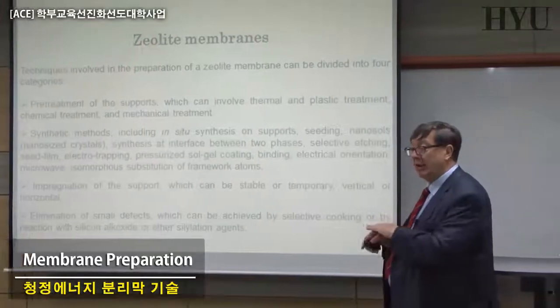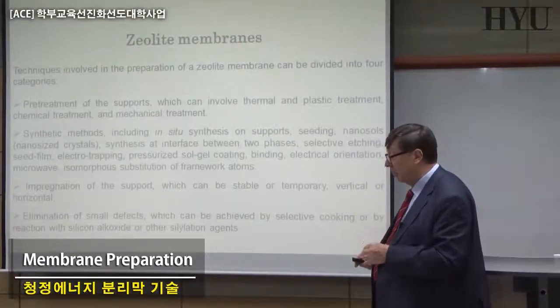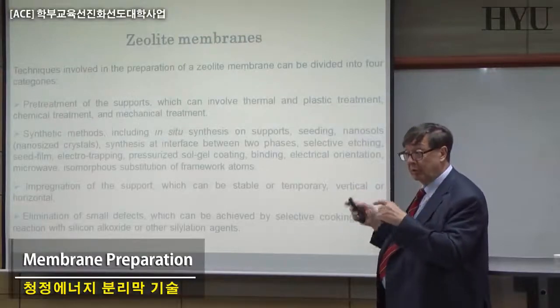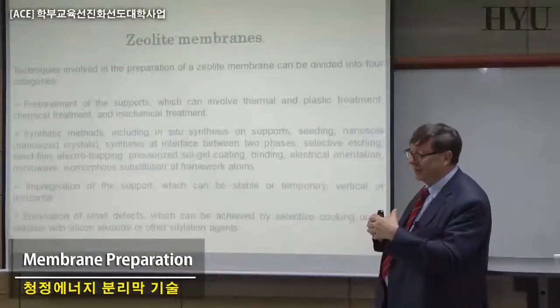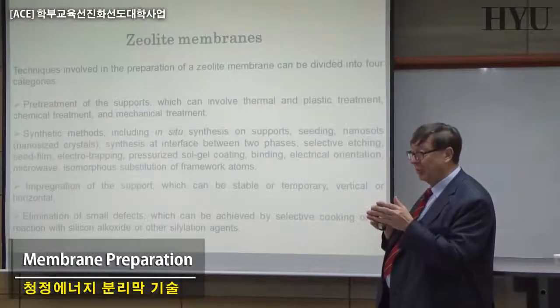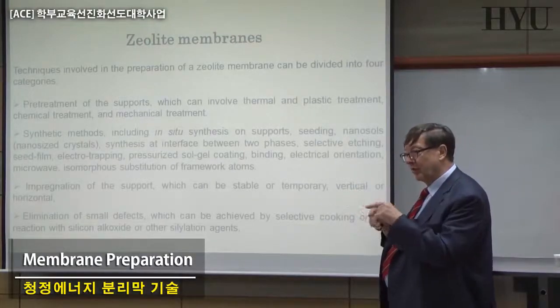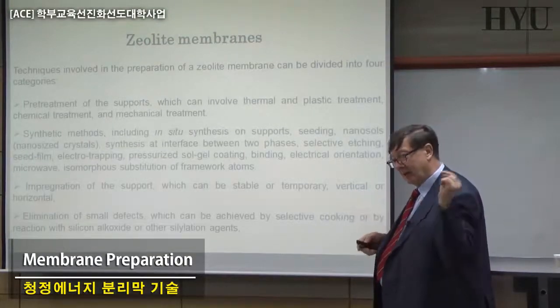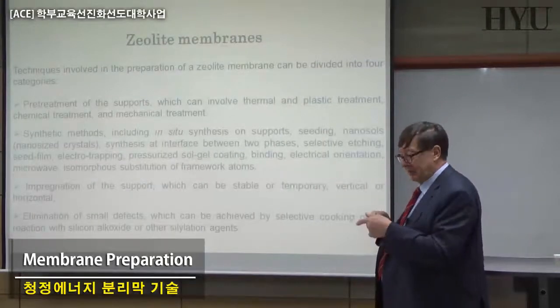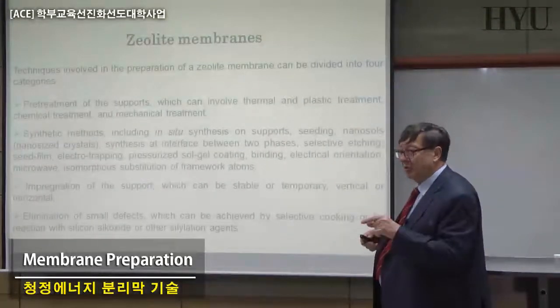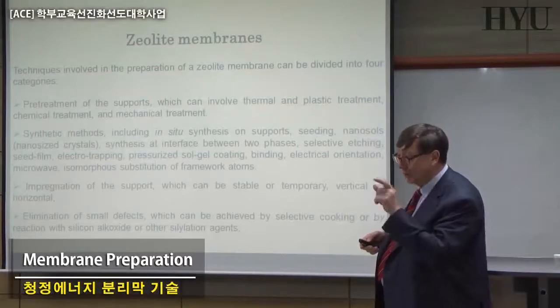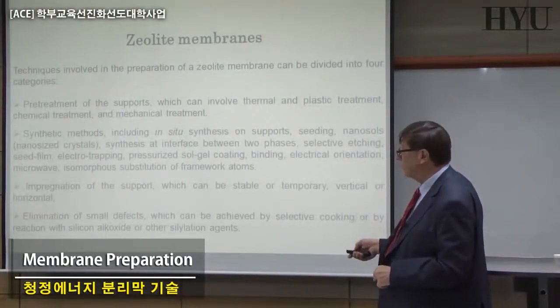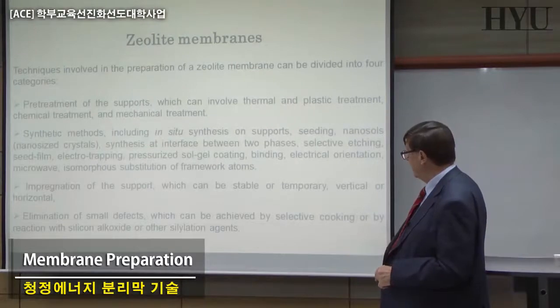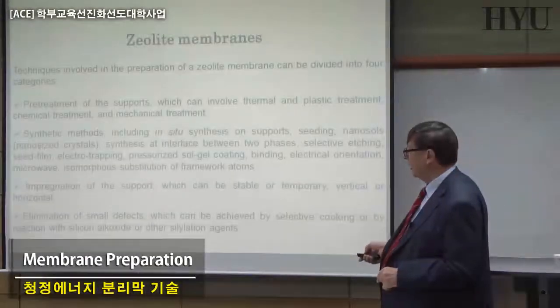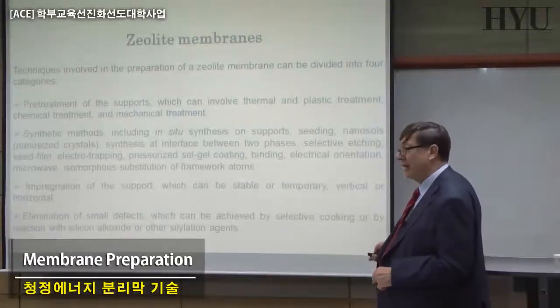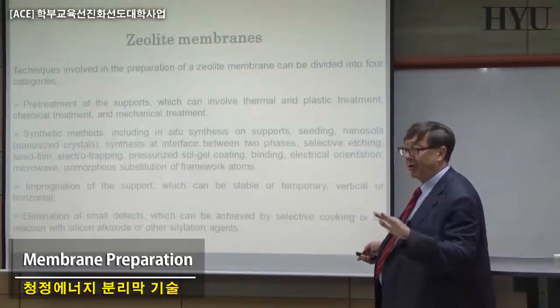film, well controlled and dense, with no defects in this case, because everything has to go through the windows, has to enter, not between different crystals. We want to avoid this, otherwise gas will move across the different crystals; it has to enter in the crystal. So you have it in such a way that nothing can go through. There is no space between two different crystals. It is not easy to realize, but elimination of small defects can be achieved by selective coking or by reaction with silicon alkoxide or other silylation agents. Eventually you can try to block the defects.